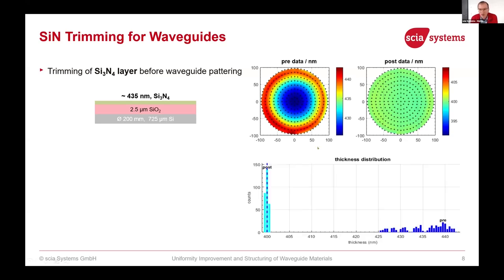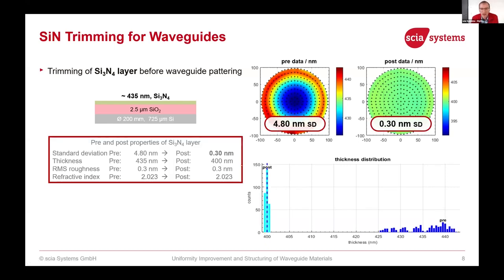To make it more visible, I have put here also a histogram. You see in the dark blue distribution the variation of the thickness over a wide range of 425 to 450 nanometers, while after our ion beam trimming, all the measurement spots are close to the 400 nanometer target thickness. So here are the values. We decreased the standard deviation from 4.8 nanometer down to 0.3 nanometer, really atomistic level, what we achieved. And I would also like to mention two other properties, like the RMS roughness, where we did not see any negative effect.